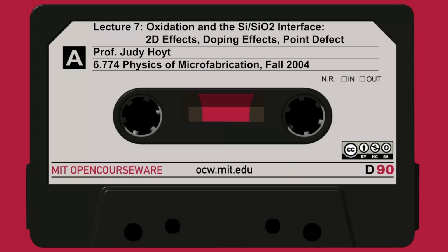So let's go to the next time step. This is sort of a time evolution, which is easy to do in the computer. Here's the oxide again after a certain period, once more, and finally, after 90 minutes, the structure is almost flat. So I achieved what I wanted in that in the flat regions out far away, in the field region here, the surface of the oxide is not at zero, but it's at a height that's just about equal to the surface of the silicon. So that's flat. But once I strip the nitride off and etch it, I still have this little bump, except for the bird's head. And if you look at this, it looks like a bird's head and a bird's beak, and the bird's eye would be right about there.